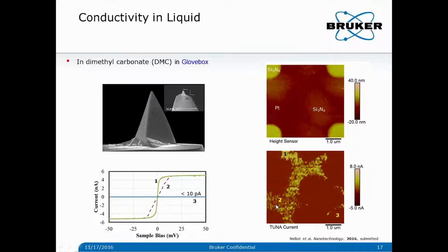We can use point and shoot to capture the IV curve at the location that we're interested in. And the IV curves captured around these three locations, number 1, 2, 3, are shown on the left here. As you can see, number 1 is the most conductive, number 2 is less conductive, and number 3 is actually on the silicon nitride island, and we would not expect any meaningful current. And that is true. The IV curve here only shows a few pA, about 5 pA background current.